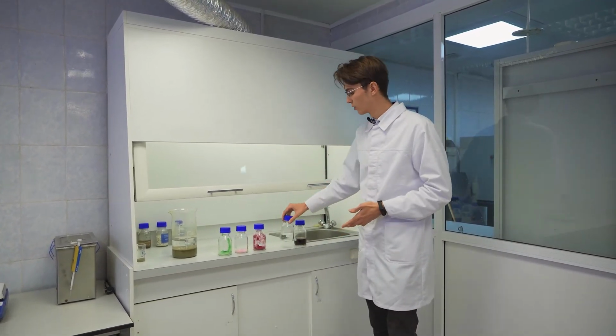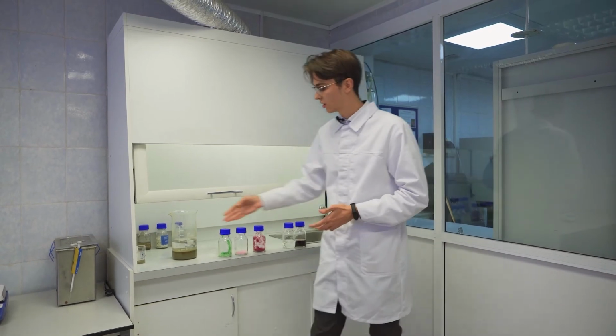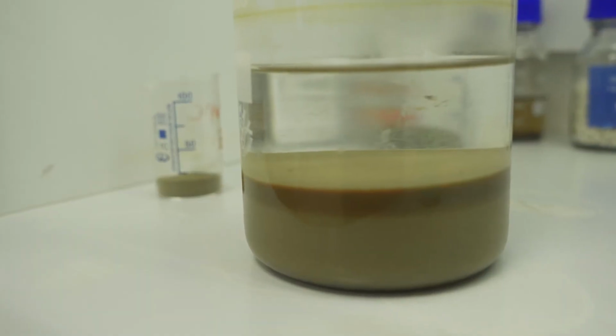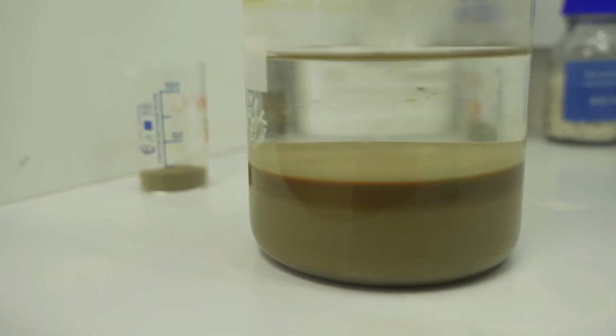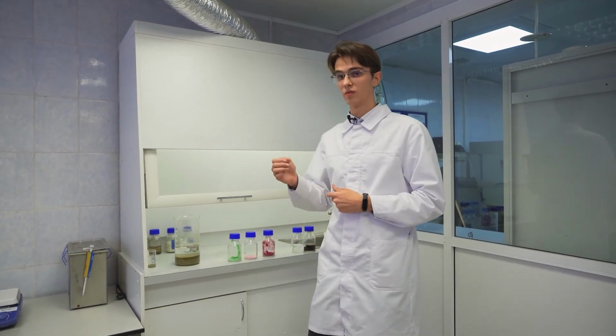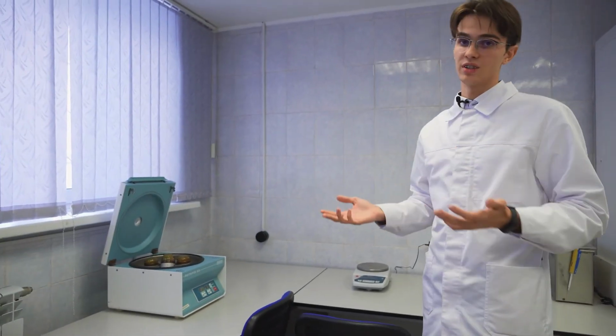In practice it looks like this, already at the end of the ion exchange reaction between these substances. We have a precipitate of complex insoluble hydroxide, which is evenly mixed. Lithium chloride remains in the solution. We don't need lithium chloride, and with the help of the centrifuge, we get rid of this solution.